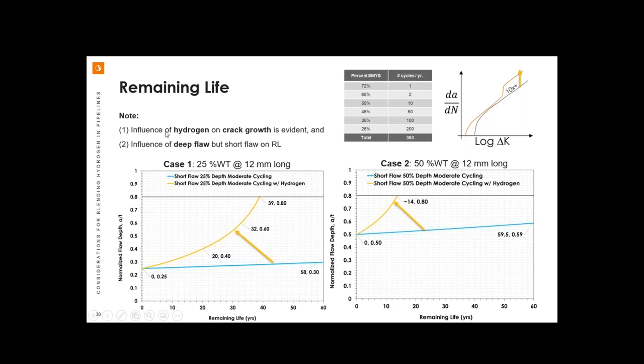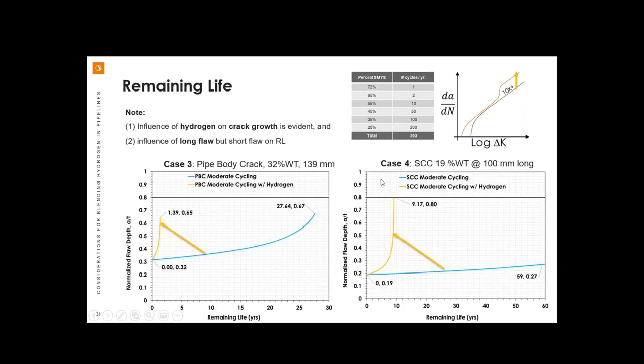So we note that the influence of hydrogen on crack growth is quite evident, and that for a deep flaw, it may lead to a remaining life, which is hard to manage from an integrity perspective. It doesn't seem to get any better for long features. Here's a feature that basically failed prior to reaching 80% depth. That's our pipe body crack at 139 millimeters, and under hydrogen service, barely lasts a year for moderate cycling conditions. The SCC feature, which we grew with the worst case from B31.12 and 579 crack growth rates, due to it being a little bit shorter, had a little bit longer life than the other one.